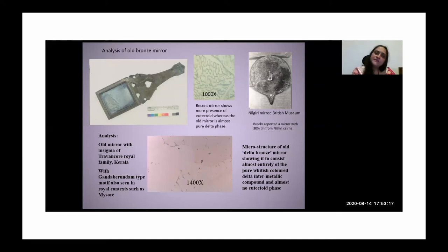And what was interesting is that when you look at that microstructure, I was just stunned to see what I saw. It is almost pure delta phase. If you look down there, it's just that white compound with very, very little alpha plus delta eutectoid network. So how they managed to achieve almost pure delta phase is amazing. When you look at the modern mirror, which was made more recently in Aranmula, you're still seeing some of the eutectoid network. So that didn't quite achieve what this particular mirror seems to have achieved, which has just gone for the delta phase. And it's difficult even to simulate it in laboratory conditions.